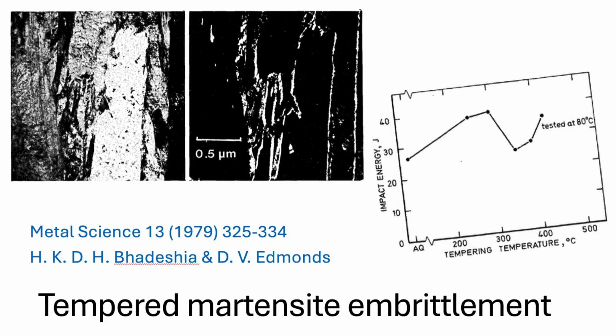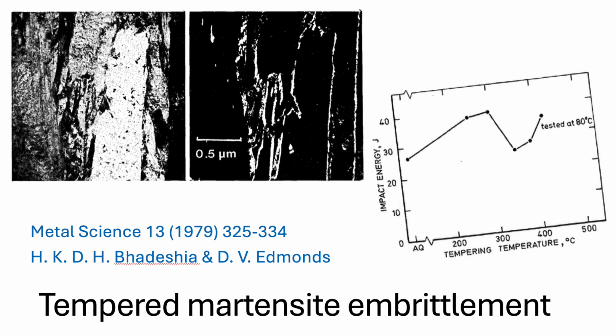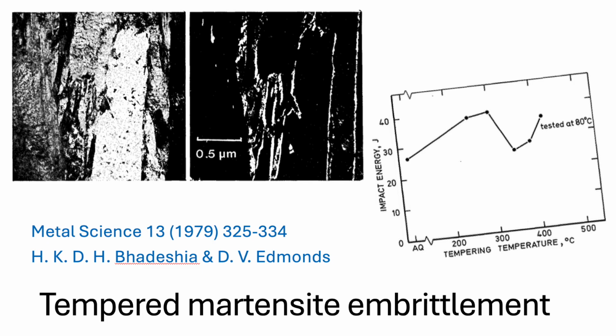Okay, so this is the massive takeaway here, isn't it? The structure that ultimately fails, that brittle cementite film acting as the easy fracture path, the cleavage path, that seems to be the common thread across all three alloys. Yes, that's the structural weapon, if you like. Right, the weapon is consistent, but the chemical trigger that creates that weapon varies completely. Absolutely. In the molybdenum steel, it's the decomposition of unstable retained austenite films. Correct. But in the vanadium and the manganese silicon steels, it's the carbon coming out of the supersaturated martensite matrix itself. That's the conclusion. It's a perfect illustration of why alloy design is just so complex and, frankly, so fascinating.